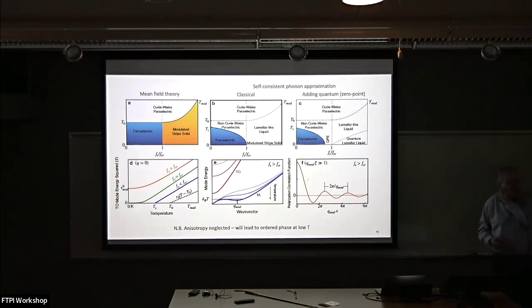And that was always a little scary because if you imagine it's sort of a double well potential, by the time the dielectric constant has got to 20,000, the coherence length for the fluctuations is a couple of nanometers. And so if you want to think about quantum fluctuations in a double well potential, you have to imagine several thousand atoms spontaneously tunneling from one side to the other. This is a bit easier because all I'm using is zero point and a very good alphas.